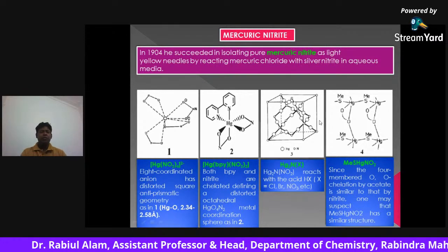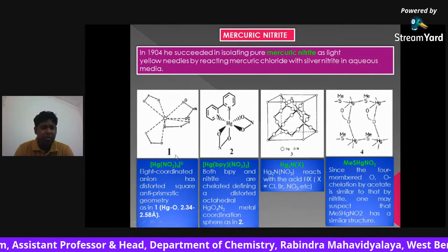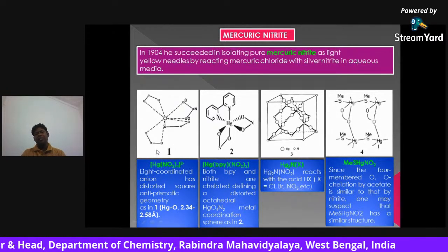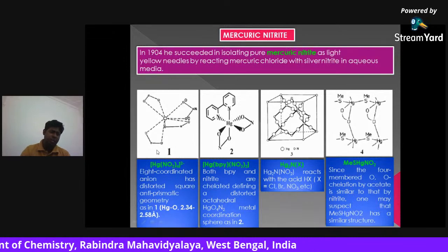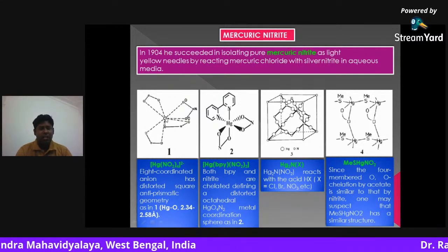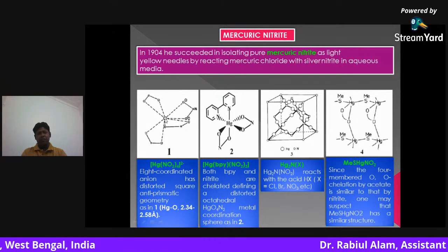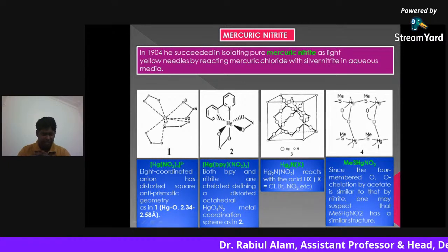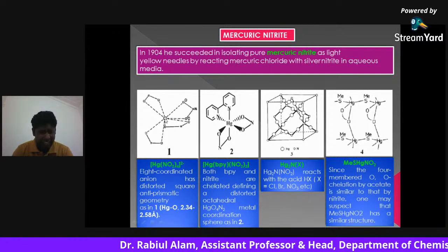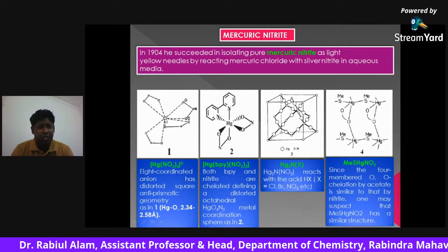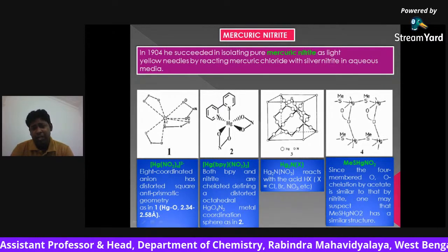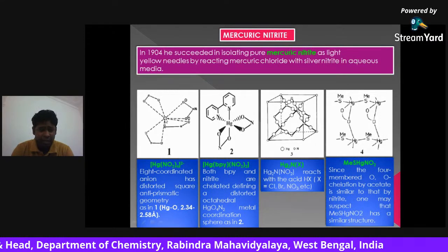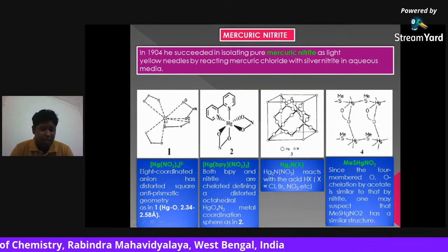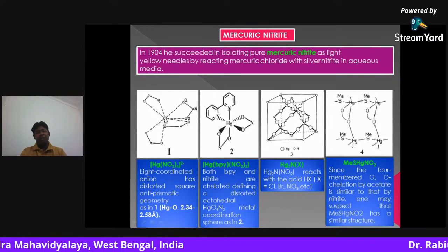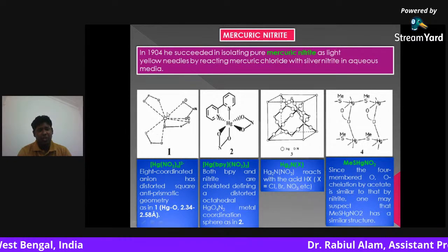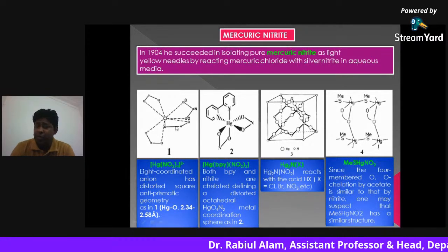And these are some compounds synthesized by Prafulla Chandra Ray. The first compound is [Hg(NO2)4]2-. This is an 8-coordinated compound. You can see that the central metal is mercury, and there are four NO2 groups which bind with the mercury center to form an unsymmetrical chelation, because the mercury-oxygen distances are not the same. They range from 2.34 angstrom to 2.58 angstrom. And this has a distorted square antiprismatic geometry.